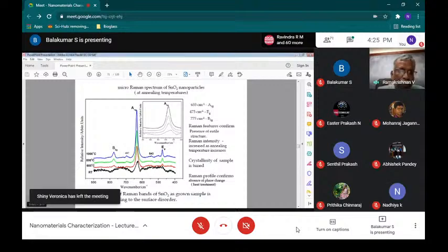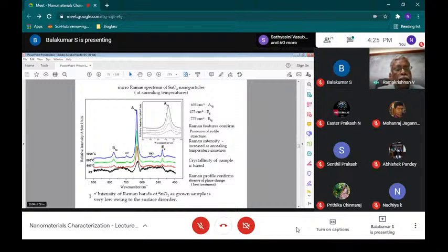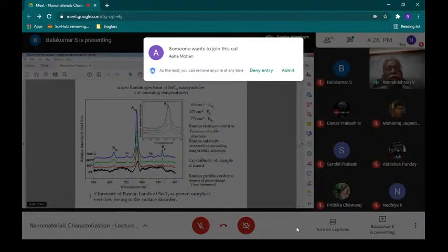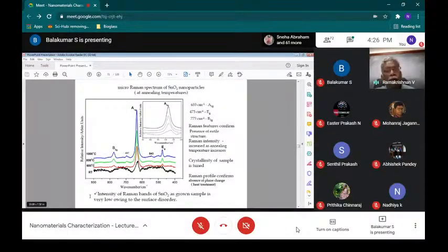So the signature remains the same. The Raman lines remain the same. The only thing is that the intensity grows and the line width decreases, becoming more and more narrow. Compared to this one, it's a very sharp peak. Intense but narrow means the crystallinity is tuned. So the conclusion, as you see from the optical image, is that on annealing, as you increase the temperature, the crystallinity is tuned, which is reflected in the very sharp Raman line associated with the A1g species at 630. That is what I also showed in the inset. Next slide.